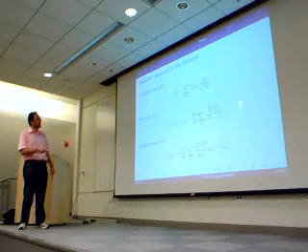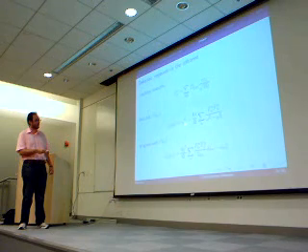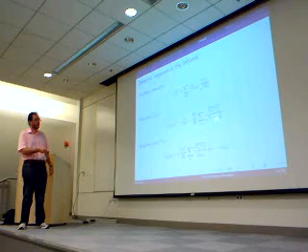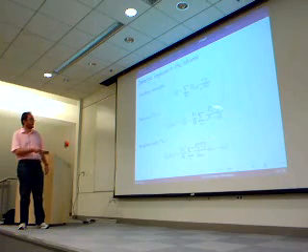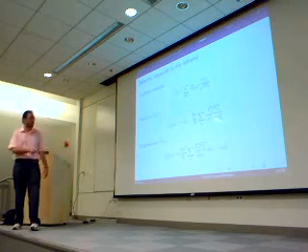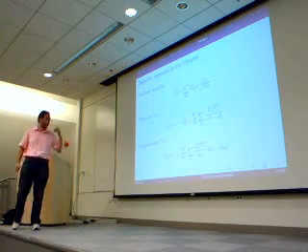The dielectric response is given in this way. We have the static dielectric, the high frequency dielectric constant, plus the term which depends on the oscillator strength and on the frequency of the light, omega, and the frequency of the vibrational mode. This formula also permits us to calculate the static dielectric constant. We just have to put omega equal to 0 here, and we see this is very similar to the formula that we have introduced.